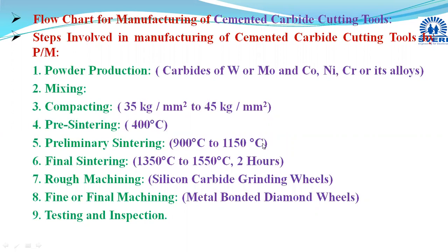And in this temperature zone, what will happen here? The strength and hardness of that component is increased, and some diffusion and densification will occur in that component. Some diffusion means little plastic deformation will occur in the powder particles. This is the preliminary sintering. Here we will get the improved strength and hardness, and then the final sintering is conducted at 1350 degrees Celsius to 1550 degrees Celsius temperature range, and this final sintering is done for 2 hours.